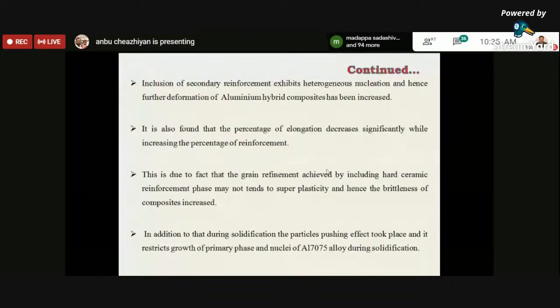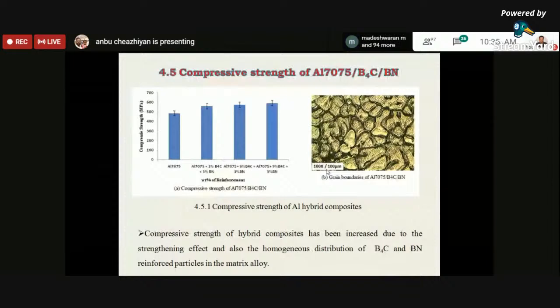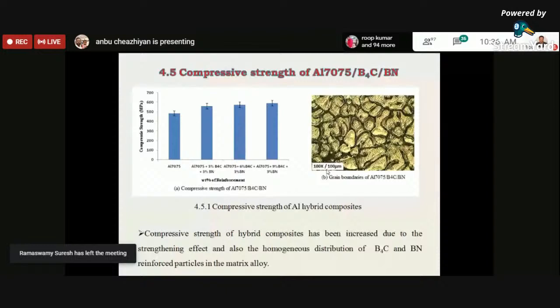And this is the compressive strength of aluminum hybrid composites. The compressive strength of aluminum hybrid composite has been significantly increased when compared to the monolithic matrix, because the matrix reduces the turning moment. So during straining, the inclusion of secondary reinforcements disintegrates the strain rate of hybrid composites, and hence the fracture surface of hybrid composites appears to be smooth. It is also found that because of heterogeneous nucleation, the deformation of synthesized composites occurs at the grain boundaries, and it exhibits plastic deformation which results in the nucleation of grains at the time of compressive loading. So you can see some of the grain refinement in that figure.